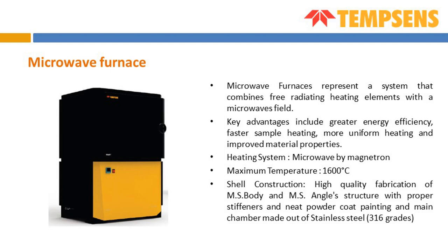Like you have some sample there. The basic phenomenon of the microwave furnace is that it is not an induction furnace. The material itself absorbs this microwave, and it heats up. So the uniformity of heating, or the temperature gradient between the inner surface of the material and the outer surface of the material, is very small compared to induction based furnaces. So the biggest advantage of the microwave furnace is that it gives very little thermal gradient between the inner portion of the workpiece and the outer portion of the workpiece.